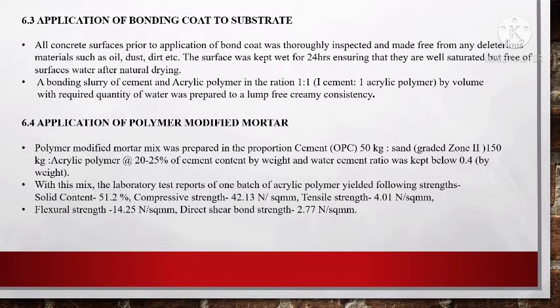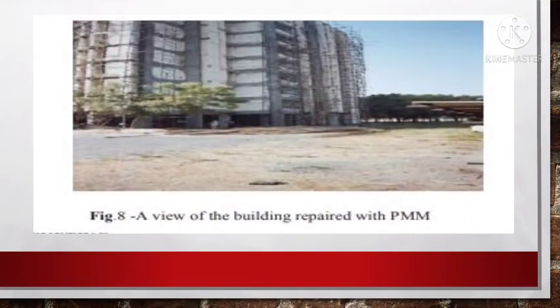With this mix, the laboratory test report of one batch of acrylic polymer yielded the following strength: solid content 51.2%, compressive strength 42.13 Newton per square mm, tensile strength 4.01 Newton per square mm, flexural strength 14.25 Newton per square mm, direct shear bond strength 2.77 Newton per square mm. And in the next figure we can view a building repaired with PMM.